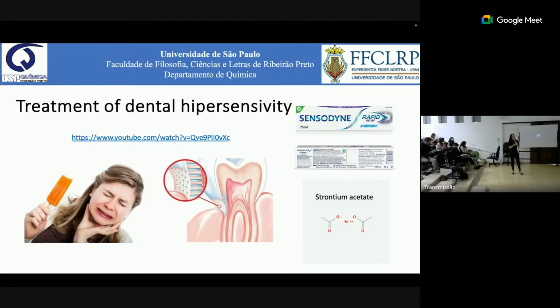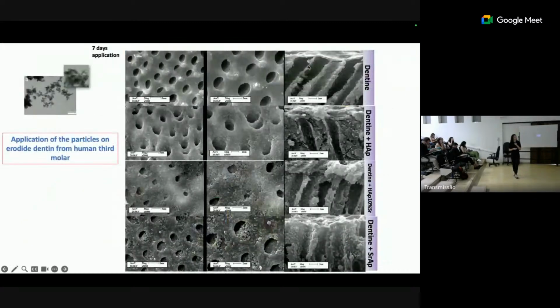I will show you the result that we had with this kind of particles to treat dental hypersensitivity. You know that strontium, in the form of strontium acetate, is the active ingredient that we find in Sensodyne Rapid Relief. So more than used for the control of osteoporosis, strontium has also been used to treat dental hypersensitivity. Then we used these kind of particles, and we applied these particles at the surface of dentin.